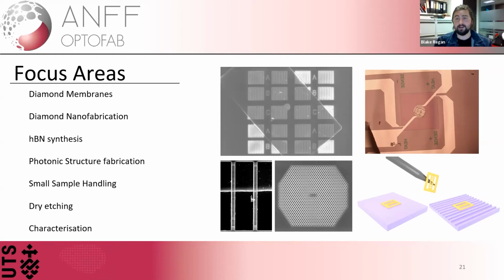The image at the top right is actually a 50 micron membrane targeted to a 5 micron area. And we did all of that by hand. The area that it's sitting on is also a very thin membrane of silicon, so we also couldn't press down too hard or we'd have cracked it. So we're quite capable with our hands as well as our understanding.